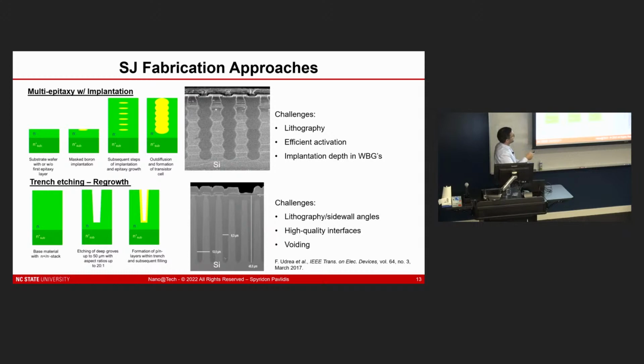And if you're in silicon, you can also leverage diffusion of the species to merge all these things and create a continuous p-n junction as well. Silicon carbide and GaN don't really have that. You basically don't have significant diffusion there. Well, silicon carbide, actually, I'll show why GaN may actually have a pathway for that later.